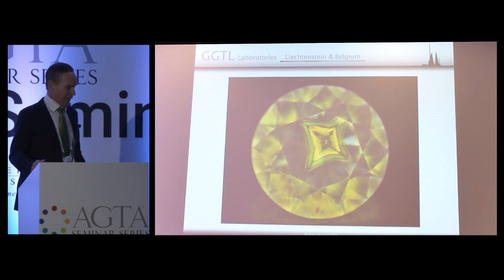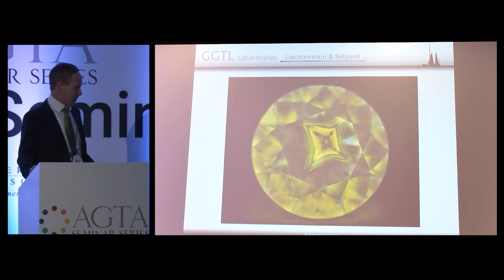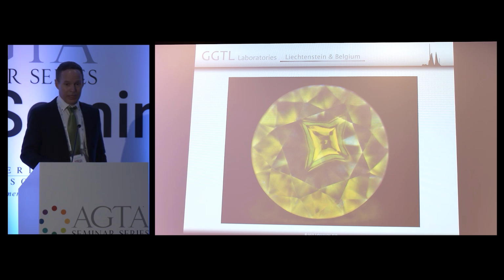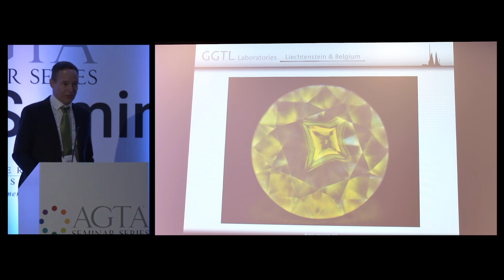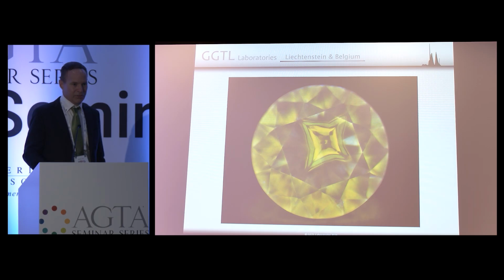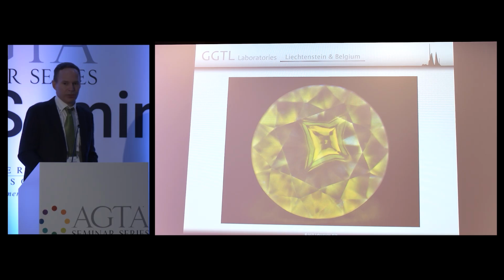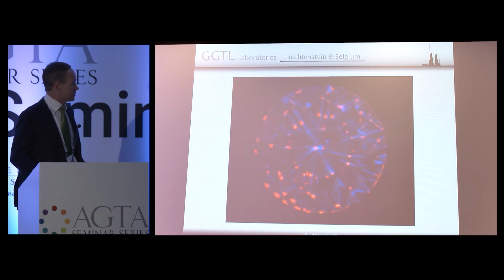Here, a spectacular example of, again, a mixed growth diamond, yellow again, with this beautiful phantom in the middle. You would think that under a regular microscope you would probably see a beautiful phantom cloud right there, but actually you don't. In the vast majority of these samples, there is nothing. So you look at this stone under regular light, there's just nothing there. And you take UV, and there it is. It shows you its growth. It doesn't always do it under an optical microscope, but just under fluorescence.